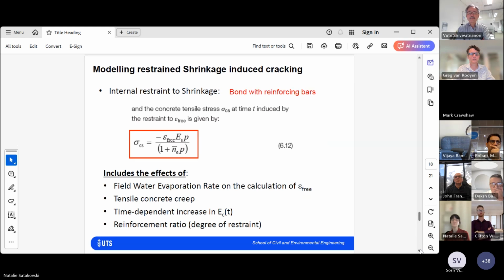I'm not going to get too much into the detail, but that equation in that document allows us to calculate the tensile stress in concrete due to restrained shrinkage. The important parameter here is the free shrinkage. The free shrinkage cannot be calculated using the Australian standard model. You're not going to get anything right doing that. This free shrinkage must include the effect of the field condition, so the water evaporation rate. We have been working on that for a while now. There are some assumptions that will have to be made: what's going to be the water evaporation rate the day following the pour and a few days after that? But it's possible to include that effect in the calculation of the free shrinkage. So that's what we do.